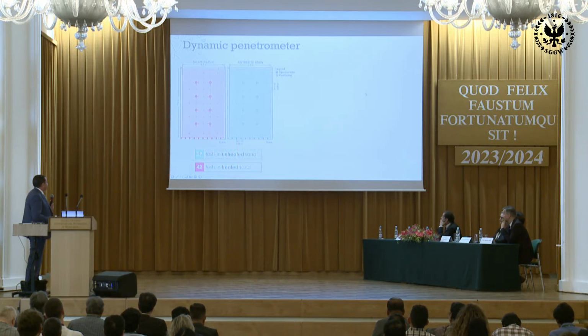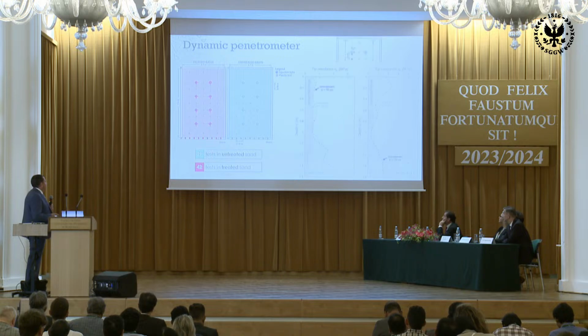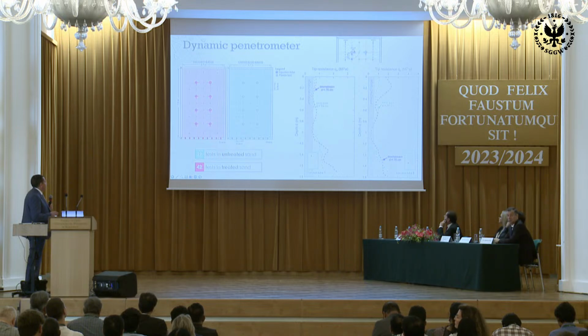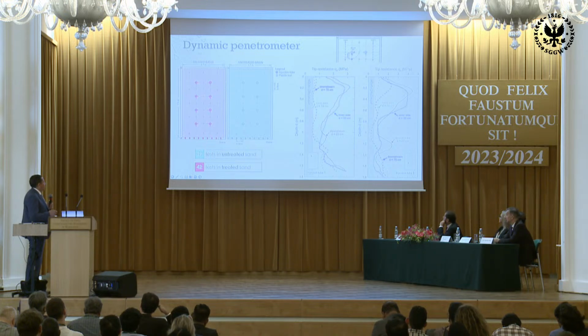And basically, the results that I will show you now are based on almost 29 untreated tests and more than 40 treated tests. So we have a large statistical database for the results. What you see here are 2 values of the dynamic penetrometer results at a short distance, 20 centimeters for one of them and 75 for the other. So they are the values before treatment, and now you get the tip resistance in the ground after treatment.